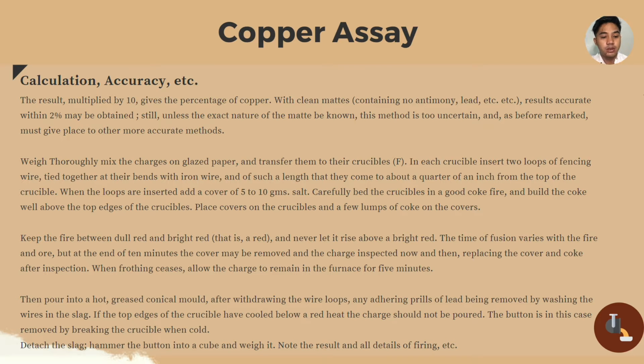Now keep the fire between the dull red and bright red, that is a red, and never let it rise above a bright red. The time of fusion varies with the fire and ore, but at the end of 10 minutes, the cover may be removed and the charge inspected now and then, replacing the cover and coke after inspection. When frothing ceases, allow the charge to remain in the furnace for 5 minutes. After that, we pour into a hot greased conical mold after withdrawing the wire loops. Any adhering prills of lead are removed by washing the wires in the slag.